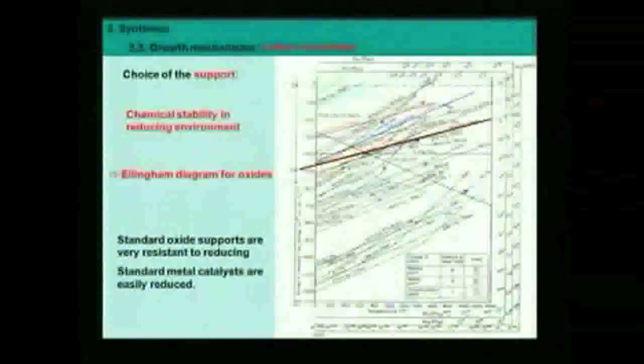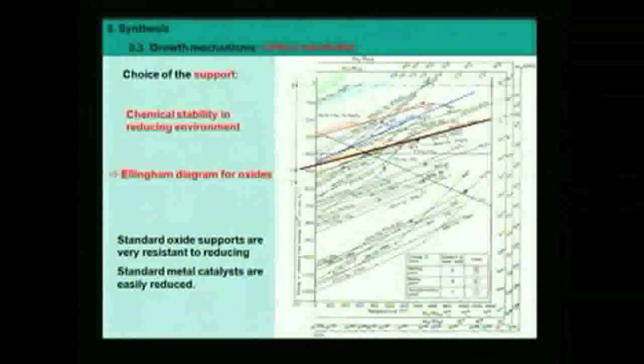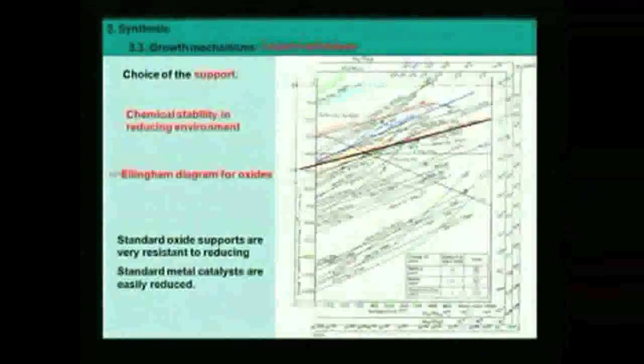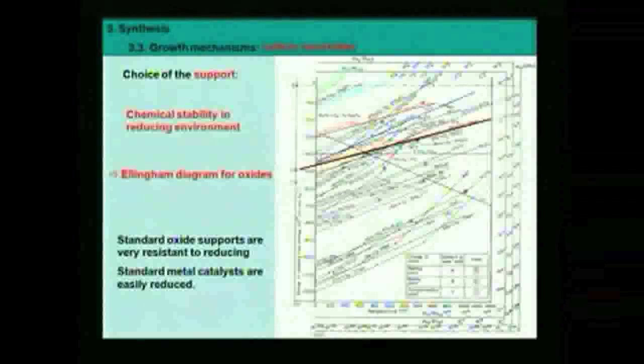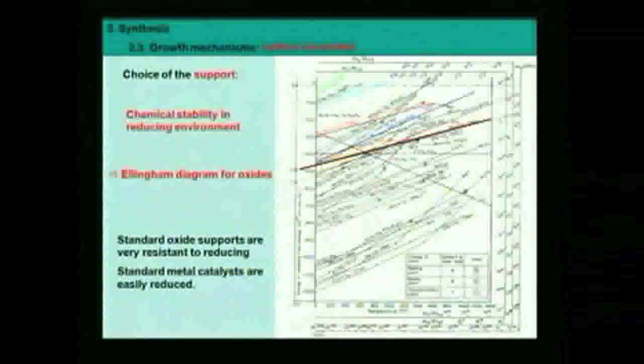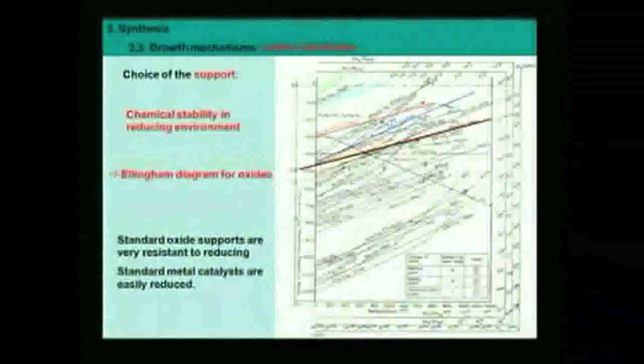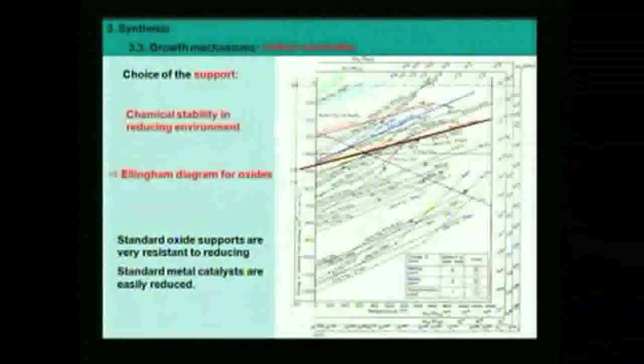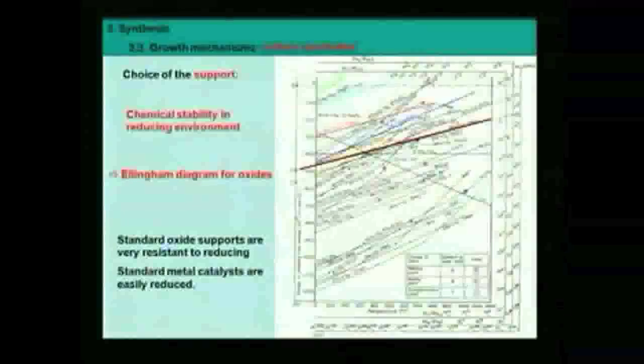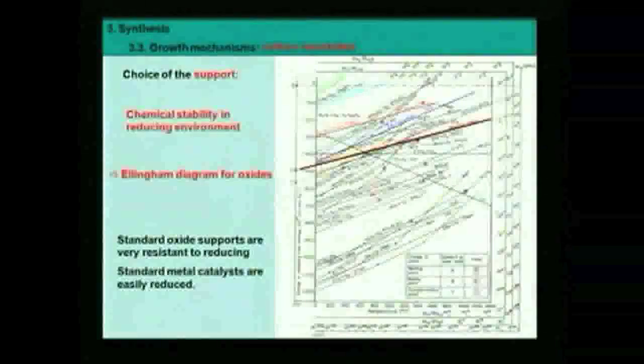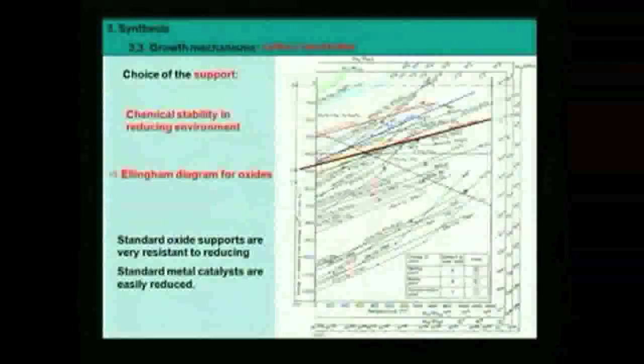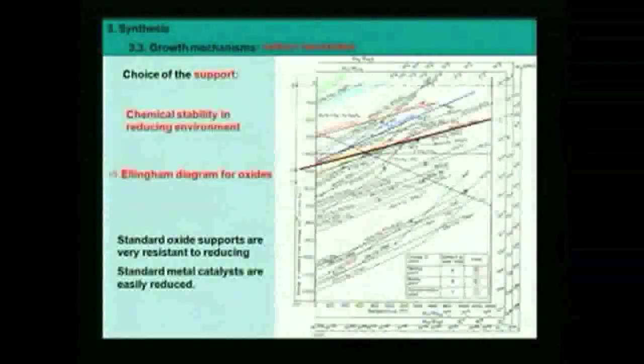It means that if I use hydrogen, this is this line, hydrogen. If I want to make water, the line for hydrogen is lower than the lines for nickel and cobalt. What does it mean? It means that I can reduce cobalt oxides and nickel oxides with hydrogen. This is what we learn from this diagram. But I cannot reduce silicon oxide and aluminum oxide with hydrogen. This is in first approximation.